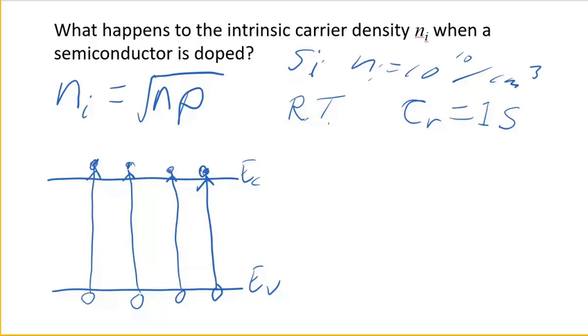Well, every quarter of a second, one of these electrons goes back down to the valence band. The electron has to give up energy when it returns to the valence band. Only LEDs give that energy up in the form of light. Normally, semiconductors give that energy up in the form of heat. A phonon in the semiconductor solid will absorb that thermal energy that equals the gap energy. So that means the solid now has a little bit more thermal energy in it, and it's gotten hotter. And hotter is something it's not going to want to keep, per the zeroth law of thermodynamics. It's going to give up a little bit of that thermal energy to the environment. So a solid is constantly absorbing thermal energy, equal to the gap energy, and giving up thermal energy to the environment, constantly.